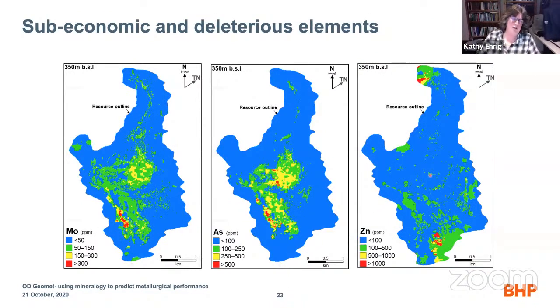We go down through and we can look at our sub-economic and deleterious elements, simple things like moly, arsenic, and zinc, which is just some of the whole list of things. We can look at the distribution of moly throughout the deposit. We say, well, there's a little bit of moly here, which is interesting. We don't see a lot of moly way up north, up in that northern part. Arsenic has a similar distribution to moly, the moly tin tungsten arsenic association. Zinc is something different, which we would expect it to be. Zinc at high levels actually impacts on copper smelting. But these are all the parameters you need to worry about.